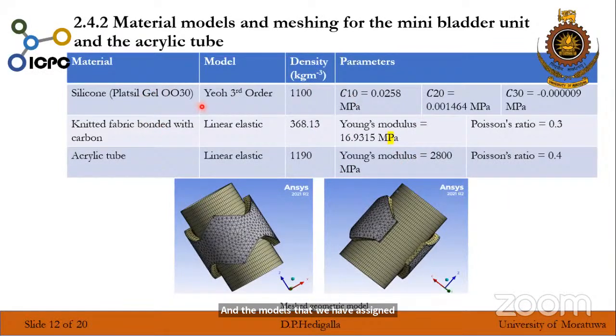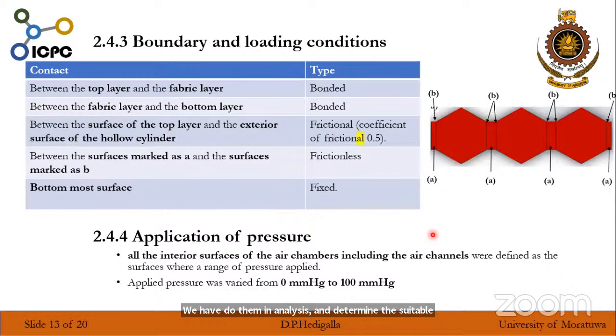Out of these parameters, the silicone and the knitted fabric bonded with the carbon fabrics parameters were experimentally determined, and the acrylic tube was determined using the literature. And for the meshing of the models, we did the mesh analysis and determined the suitable mesh size for that. Once meshing was done, we needed to assign the boundary and loading conditions.